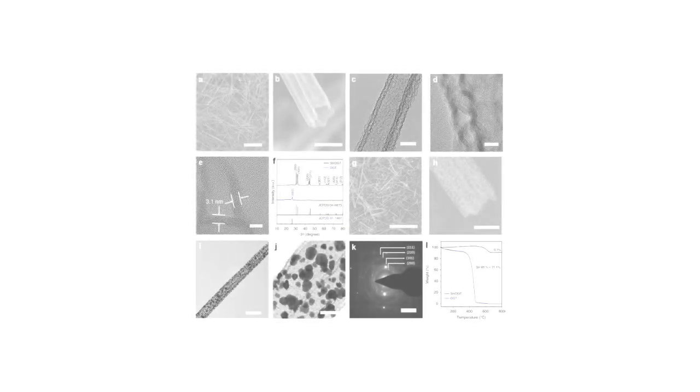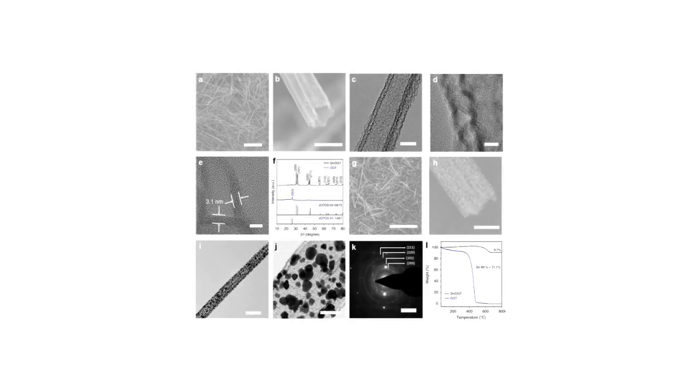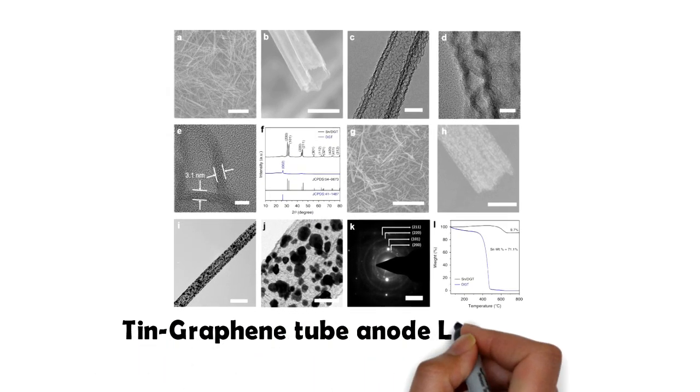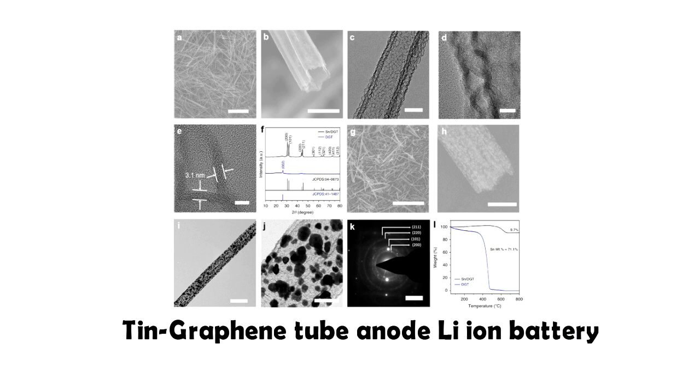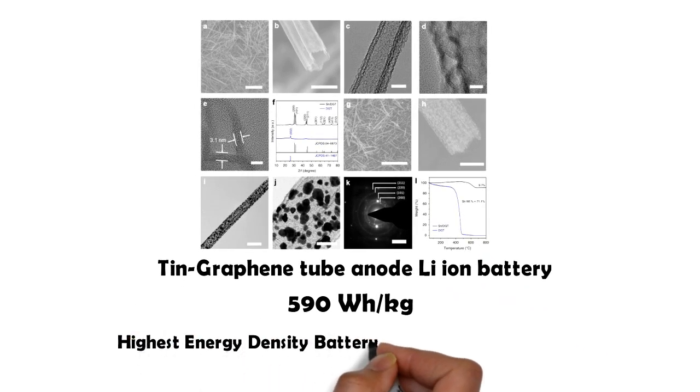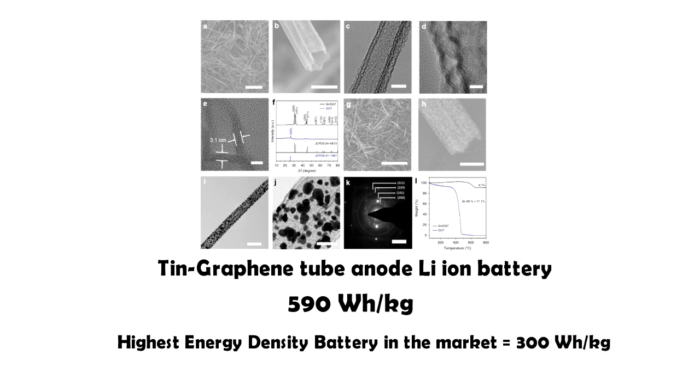In academia, there's also research being carried out on lithium-ion batteries with graphene added in some shape or form. There is the tin graphene tube anode lithium-ion battery that tested for 590 watt-hours per kilogram. This is almost twice the energy density of current batteries in the market, with high cycle life. Similarly, 30% higher capacity was recorded by using a graphene-enabled silicon-based lithium-ion battery. Links to both these articles are in the description.